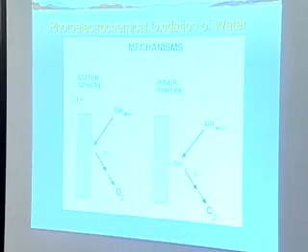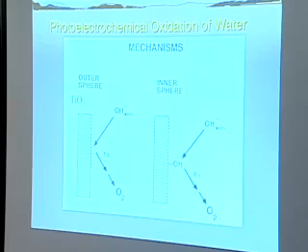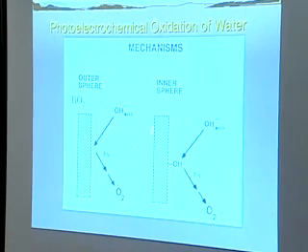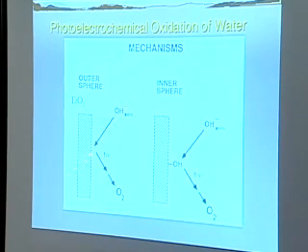And the question we were asking in the late 80s was, is this a process that goes by an inner sphere mechanism in which the electron doesn't transfer until something like a hydroxide or a water, I'm showing hydroxide there, but it could be a water, it depends on the pH, obviously, attaches to the electrode, and then through a series of steps is oxygen? Or is this an outer sphere charge transfer, where all that has to happen is the hydroxide or the water hits the electrode, and out comes oxygen?